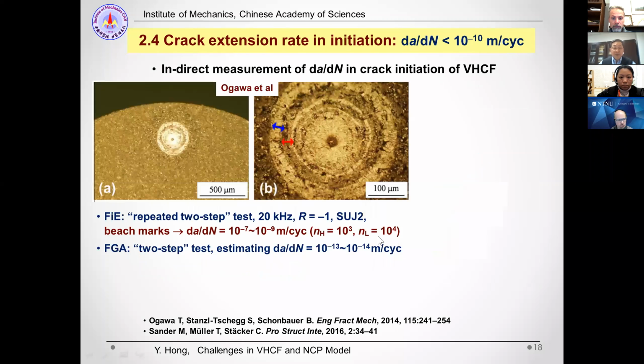Another indirect measurement uses a kind of repeated two-step testing, and they are able to catch the beach marks on the fracture surface, but their measurement is the area of the fisheye region beyond FGA, the initiation area. So they obtain the data in this region, and then they try to infer, or estimate, the crack extension rate in the initiation region, and give the result of between 10 to the minus 13 and 10 to the minus 14 meter per cycle.